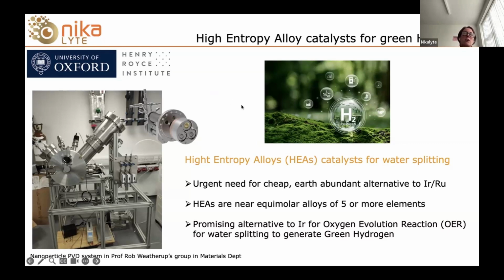And the project was designed to look at novel catalysts as a replacement for expensive iridium and ruthenium catalysts for water splitting. And the particular materials that were identified as a cheap and earth-abundant alternative are high-entropy alloys. So high-entropy alloys are near equimolar alloys. So there's no dominant element in that alloy. They all have equivalent ratios.